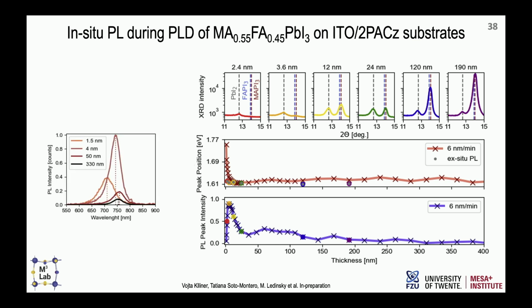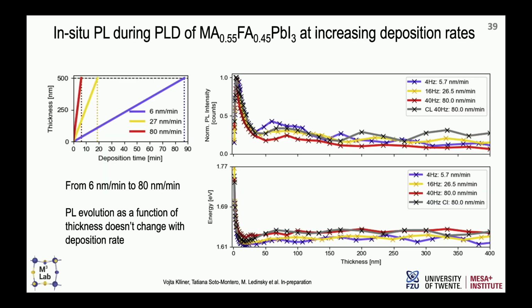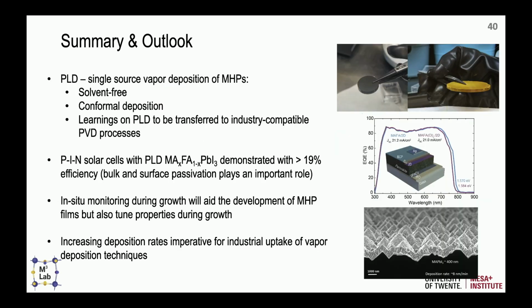This is what we learned from the standard deposition rate, but now we want to go for much faster deposition rates. If we do the same measurement at increased deposition rate, we see that the trend is exactly the same. I'm not going to go into detail, but the most important thing we learn at the moment is that if we increase the deposition rate to make a film of 500 nanometers in around 5 minutes, the PL and the growth are almost the same. That gives us a good insight to say we should really optimize it to go for very fast deposition. But that's work in progress.